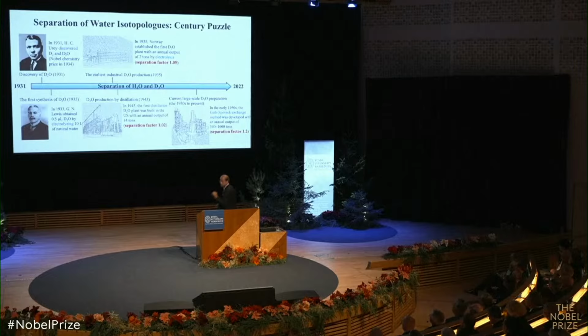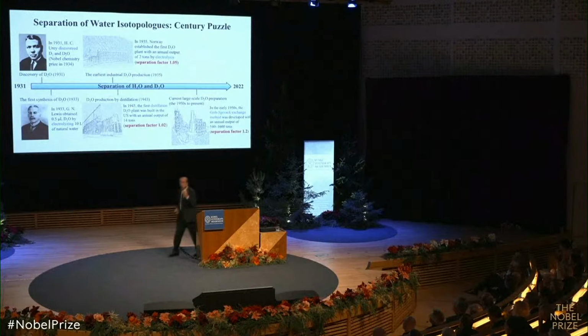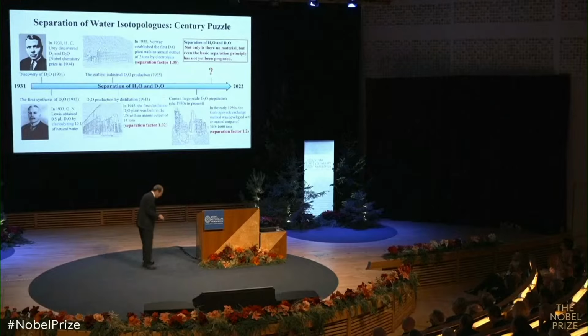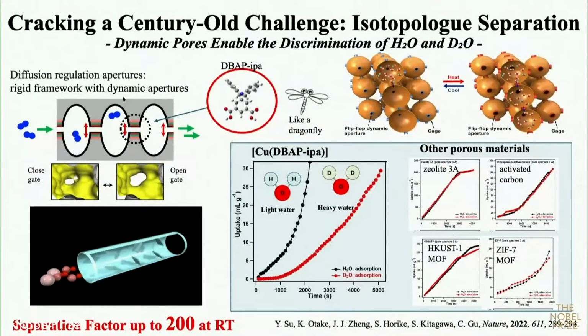Because a separation factor of 1 means it is theoretically impossible to separate. Only a small difference, 1.05, 1.2, even the current system is 1.2. So we need to develop or discover a better mechanism. So this is a big issue. So we synthesize this type of porous structure, big pore and small channels. On the small channel, we put this type of local motion ligand. The motion is just like a dragonfly. So using this channeling system, we try to separate these materials.